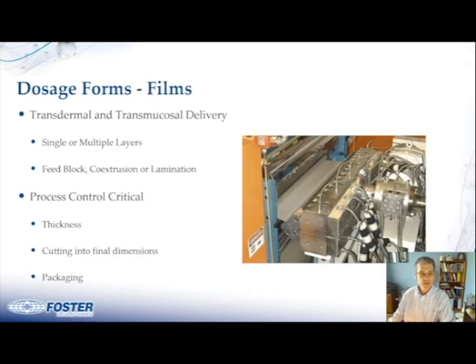Films are another dosage form, so they can be used for either transdermal or transmucosal delivery. They can also be used for implants. They can be single or multi-layers. You can use a feed block co-extrusion or lamination. Process control is critical to, again, control the thickness for the reasons I mentioned earlier. You need good dimensional controls. You have to cut these into the final dimensions using some sort of cutting device and then packaging equipment.